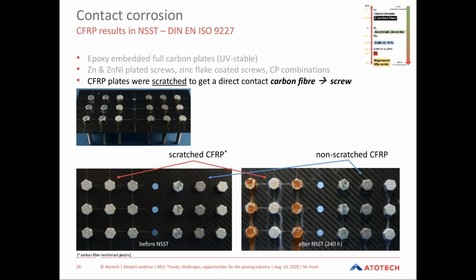There is another special feature to be mentioned, namely that the plates were scratched before they were fitted with the screws. Why that? As already mentioned, the plates are made of epoxy-embedded carbon, in which the epoxy can act as an insulator. In real life, we all know that when we screw, we destroy at least part of this epoxy insulation and get a direct contact with the carbon. So we forced this contact by scratching the boards to make our test in our tech center more real and closer to real life.